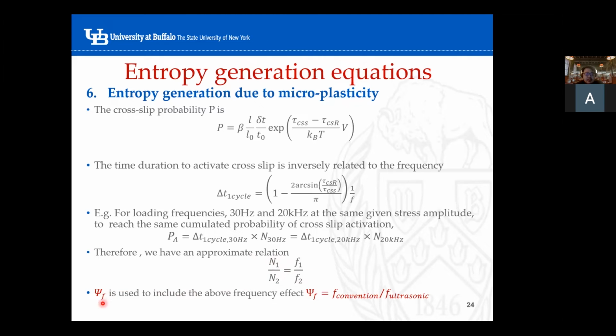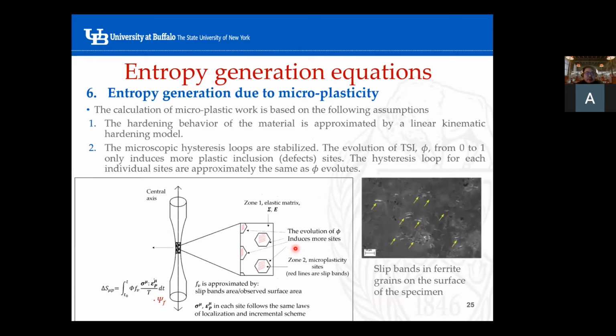By obtaining this positive relation, we use the psi_f factor to include the above frequency effect. The psi_f factor is basically approximately the conventional operating frequency divided by the ultrasonic vibration frequency, used to include the frequency effect. So everything is the same here, but the only difference is that in the microplasticity model...